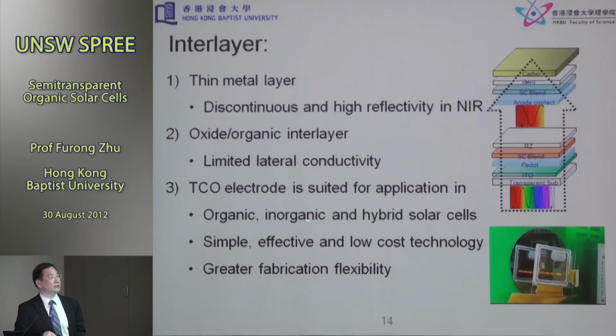And we can deposit a high quality transparent conducting oxide on the oxide material, because it has a very high conductivity and also very good transmittivity in the visible wavelength range, all the way to near infrared. So this is very useful, and depositing or sputtering of ITO is a very well established technique. It can be easily explored and expanded for application in future mass production.